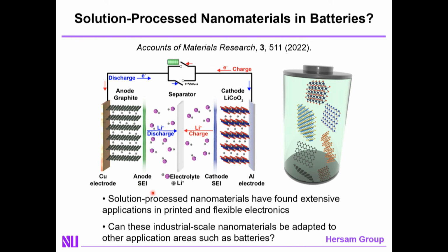These are layers that build up at the surface of your electrodes during electrochemical cycling. They are generally deemed to be problematic because they lead to a reduction in capacity as a function of cycle time and will ultimately limit the lifetime of your battery. So our thinking was what we should do is replace this structure with a mixed dimensional heterojunction, where we're still going to use a 3D bulk material for the cathode, but put an artificial SEI made from a two-dimensional material on the surface. And that way we will control and hopefully improve the cycling performance of the lithium-ion battery.